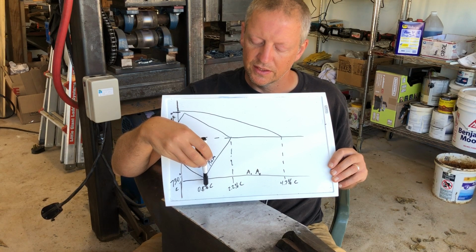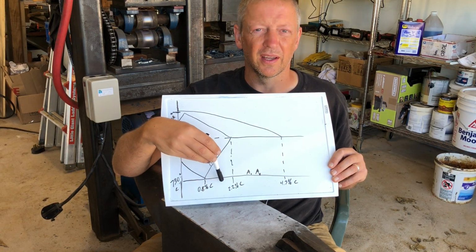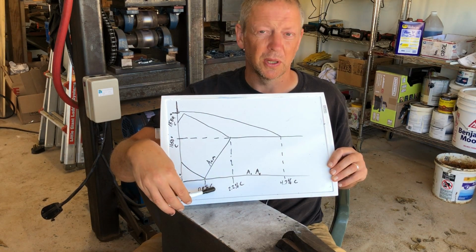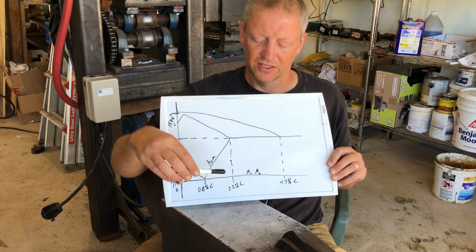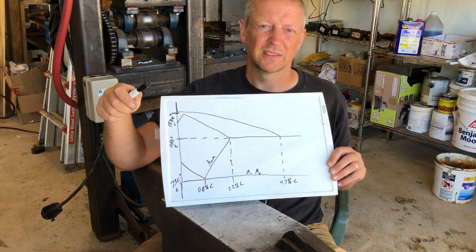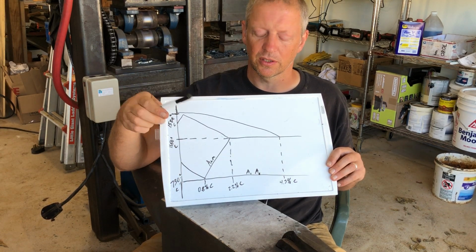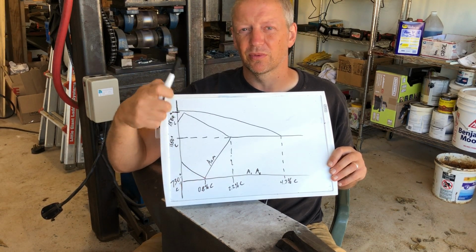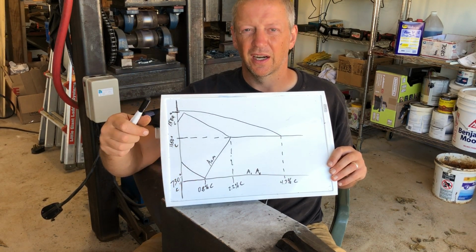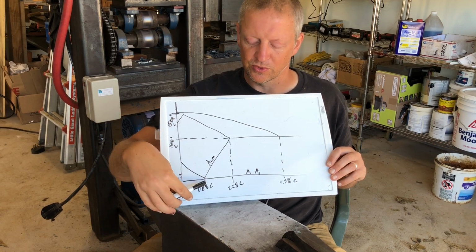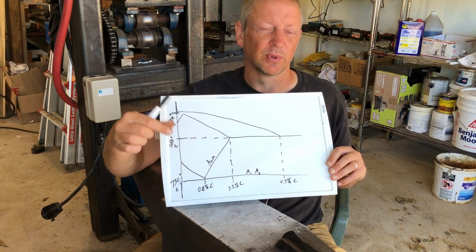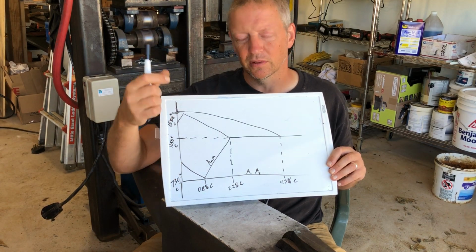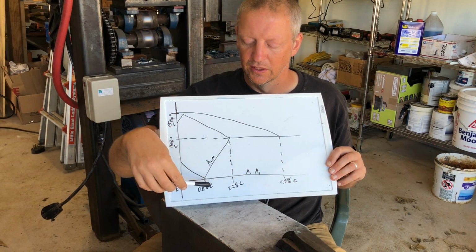And to the other side, you will have a mixture of perlite and just free carbide, not associated with the perlite structure. The perlite structure is a fixed ratio of iron to carbon, which is why 0.8% is our eutectoid point. You get pure perlite at that point, equilibrium and all that.